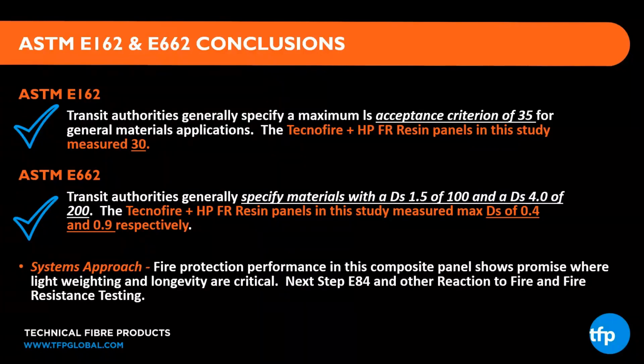And then the E662, you're looking to specify materials in the transit authorities with a Ds of 100 maximum, and at 4 minutes, that was for the minute and a half, sorry. And at 4 minutes, the Ds, the smoke opacity, of 200. So we reduced down the Ds on the minute and a half to 0.4 out of 100, and we reduced the other one down to 0.9 after 4 minutes. So 0.9, when you think about the maximum allowed is 200, we're really at just a fraction of that. There are a lot of other components that you might bring into a train floor that might add to that. So we are not going to contribute to that.